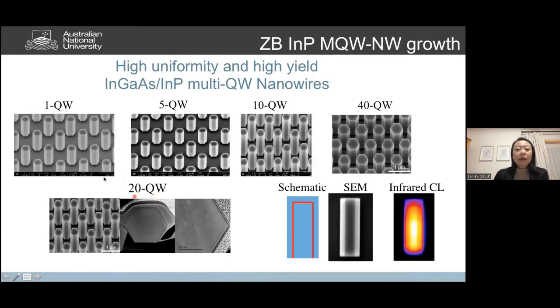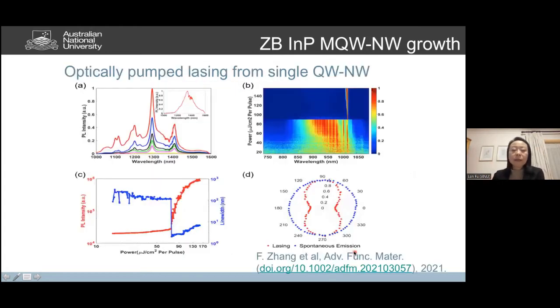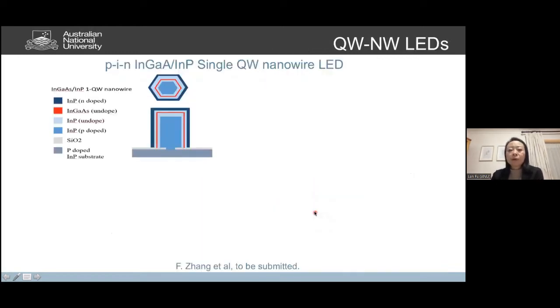So based on this, we can in fact incorporate many more quantum wells. We have done that up to 40 quantum wells, with very nice, beautiful nanowire shape. This is the cross-sectional TEM showing that. And if you look at the infrared cathodoluminescence measurement, you can see that we have very nice emission along the length of the nanowires from this zinc blende-based indium phosphide quantum well growth. And with optical pumping, we can also see very nice single nanowire lasing from the quantum well at 1300 nanometers. So that basically shows the very nice optical properties of the quantum wells.